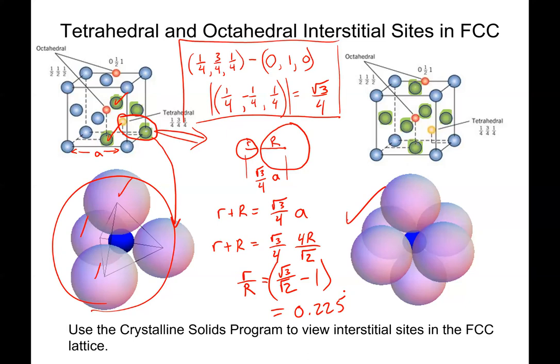Okay. So what does that mean? So if I have the radius of my host, let's say that it's iron, I can go ahead and put the radius of iron in here. And approximately two tenths of that iron radius would be the radius, maximum radius of my interstitial that would just fit into this tetrahedral site without needing any extra room. Now, it's not the maximum size of an interstitial atom that can fit in real life, because you can fit bigger ones in there. They'll just distort the lattice. But by distorting the lattice, I won't be able to put as many into the overall structure. If they are small enough to just fit inside the interstitial without stretching the lattice, then I can get a lot more of them into the structure. But this is the size of this hole that is in the structure.